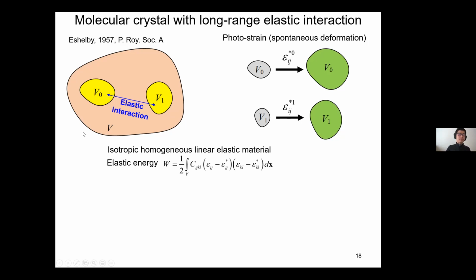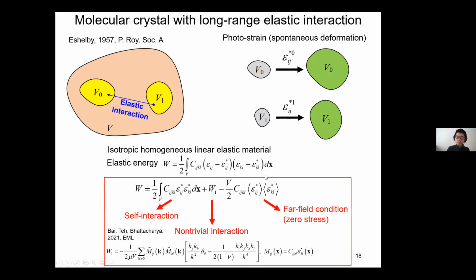So if we write this material as an isotropic homogeneous linear elastic material, just as in classical elasticity, you can write the elastic energy. You can actually solve this elastic energy analytically. That's what we did. This is the analytical result in the infinitely periodic supercell. It has three parts in the end. The total elastic energy has a self-interaction part, and then there's a non-trivial interaction part, which you can write out in Fourier expansion. And then there's a far field condition. In this case, this is like a boundary condition. In the far field, I apply no stress, okay?